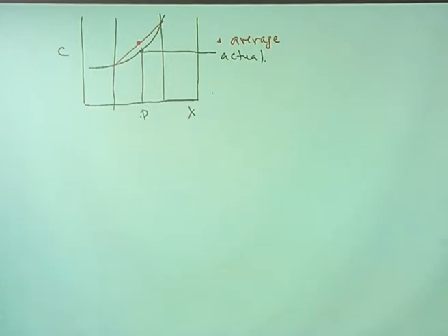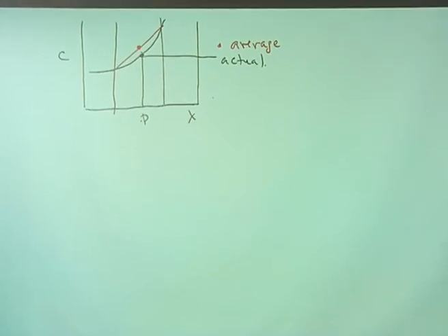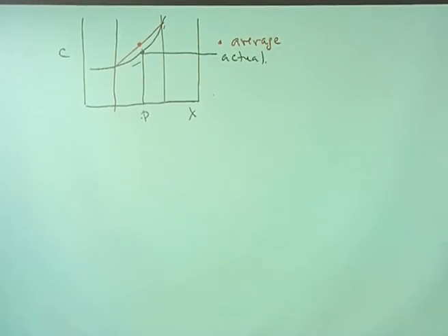And so what it says is that if I give you material of composition exactly equal to that black dot, an atom sitting there in the system with this curvature in the composition profile says that, well, that's not the right composition, because I can sense that the atoms around me are not equal to the average, and that average composition of the atoms around me is not equal to the composition at P. And so what you might expect is that the chemical potential will be somehow proportional to the curvature of the composition plot. Okay?